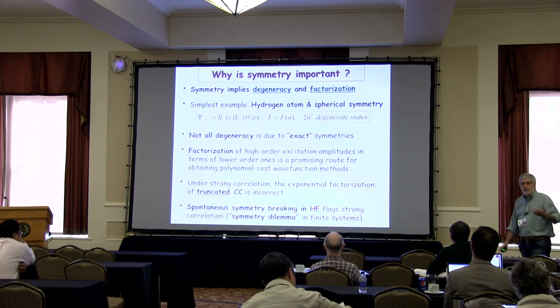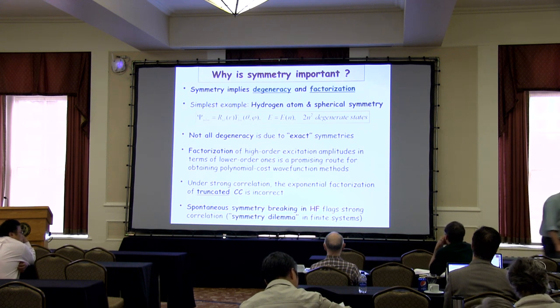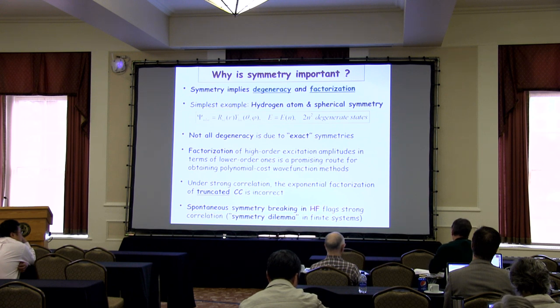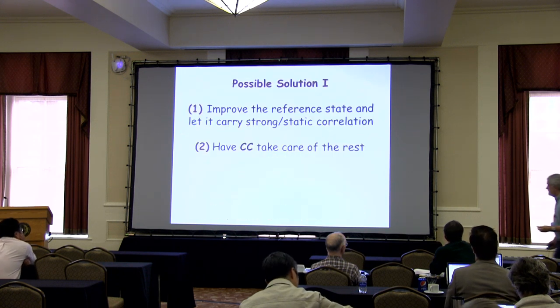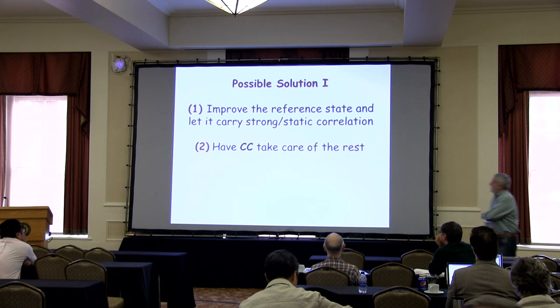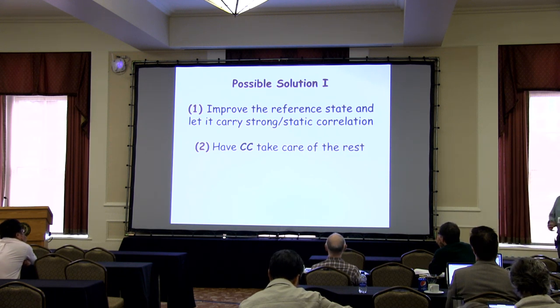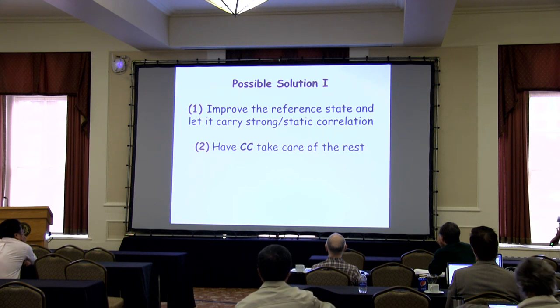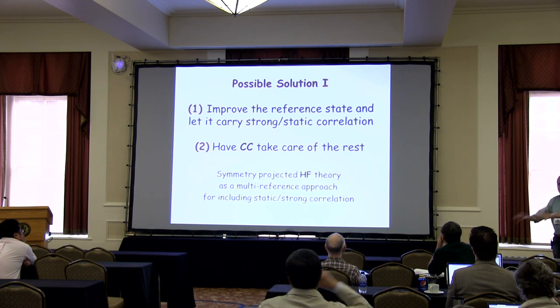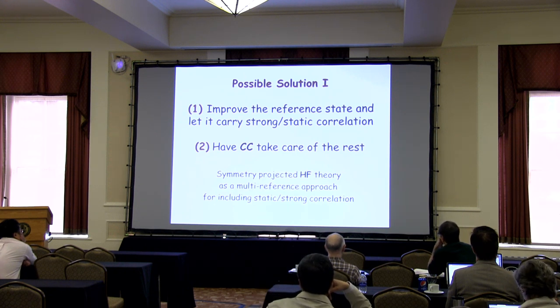What was happening, it's a long story, but I'm going to just say a few things only. Why do we believe that these guys are strongly correlated? Because it turns out in our view that what makes the network of carbon bonds happy is short-range antiferromagnetic spin-spin interactions, like in graphene, for example. When you put a pentagon there, you produce frustration. You cannot just go around up, down, up, down, up, down. When you start doing that, you mismatch. So there's geometric frustration because of the pentagons. And that, we believe, causes issues.